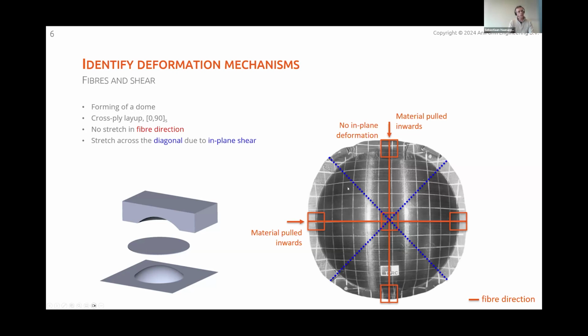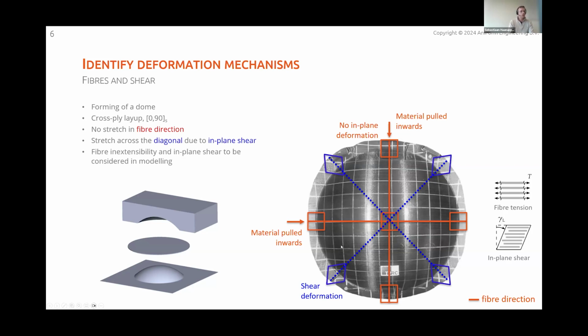On the other hand, if we draw diagonal lines here, we see some extension or stretch, and that is due to some in-plane shear that is developing here. You can clearly see that in the corners, that these squares are actually not squared anymore. So what we see here is that there's some fiber inextensibility, which we need to describe, and there's in-plane shear going on, governing this forming process of this dome. So these mechanisms for sure need to be considered in the model.